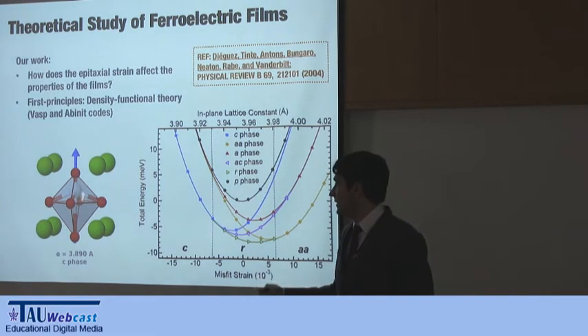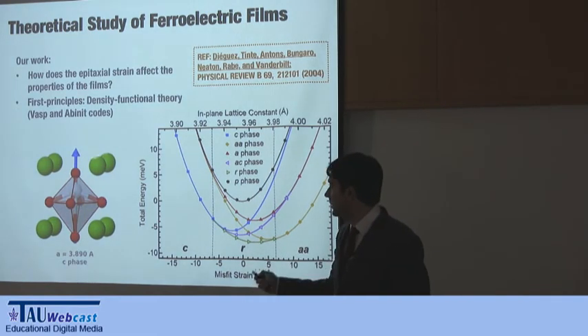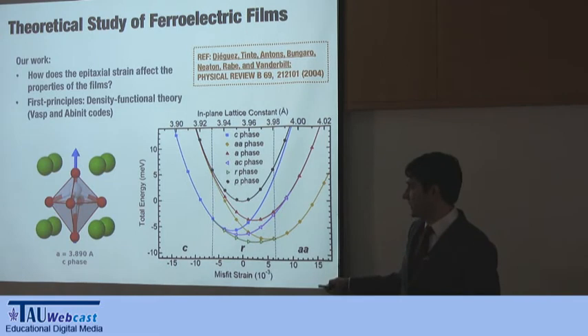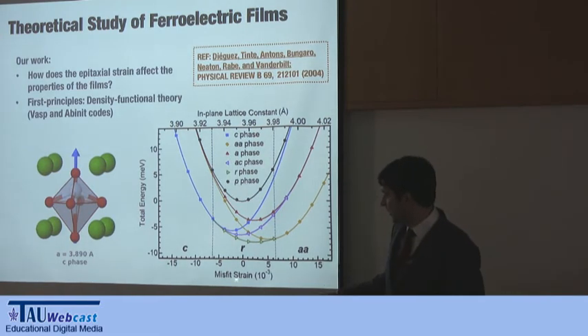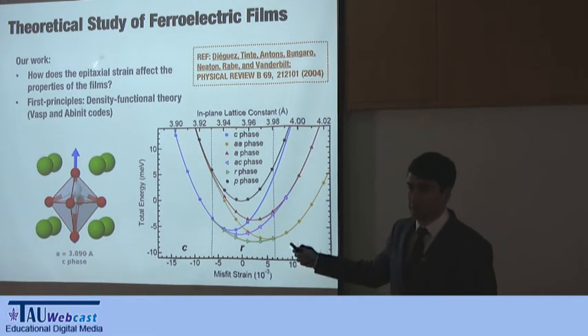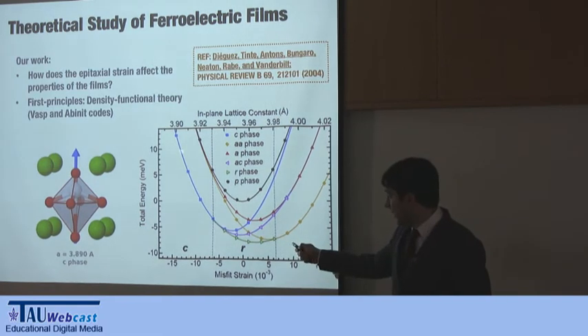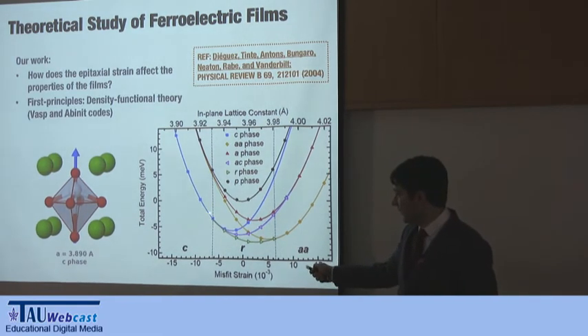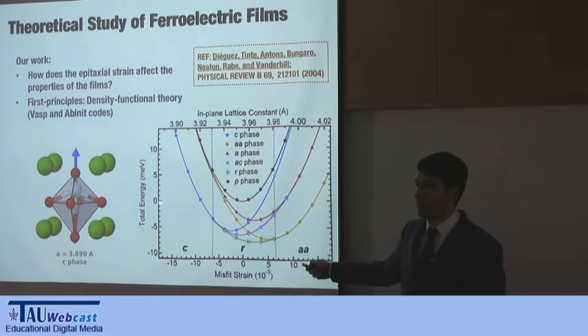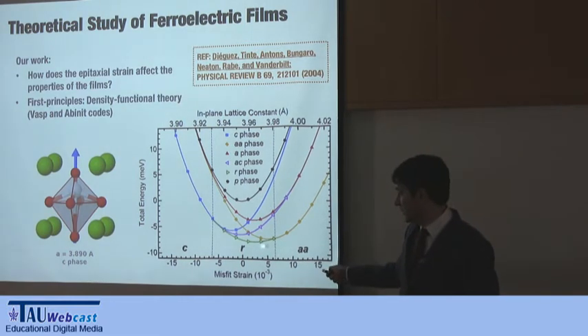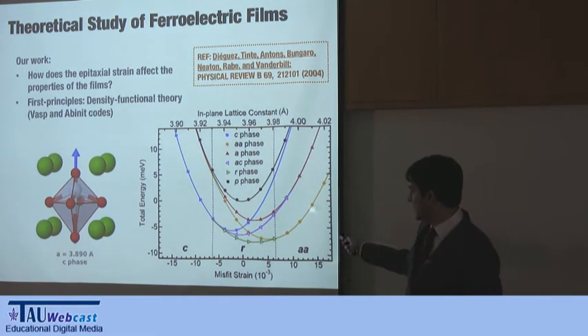So we want to see in this case what is the effect on the polarization. I mean, how does the polarization change with the strain? So when there is a lot of minus, that is compressive strain, when you squeeze this, the central atom goes up and you have a polarization in this direction. You can simulate this for different degrees of strain, and there is a point in which there is a phase transition. This curve that corresponds to this phase is not anymore the most stable one, but there is what we call here the R phase that takes over, and then there is the AA phase.